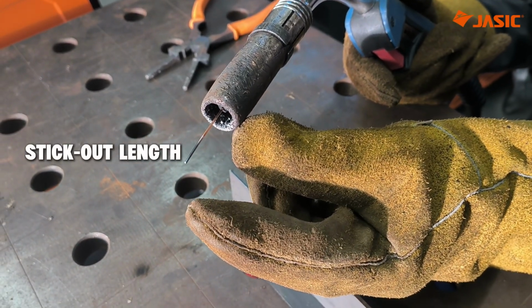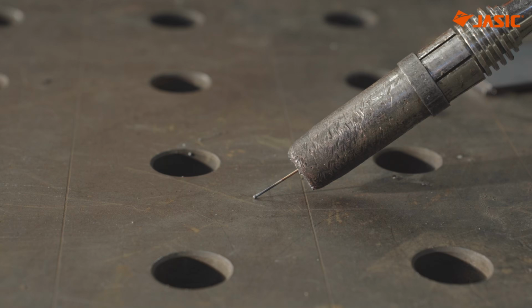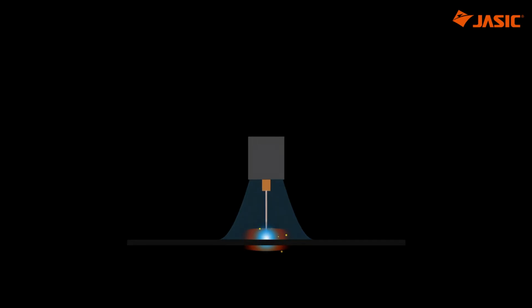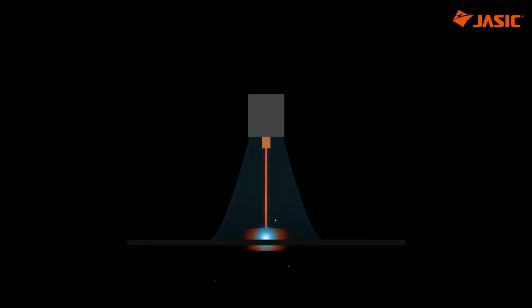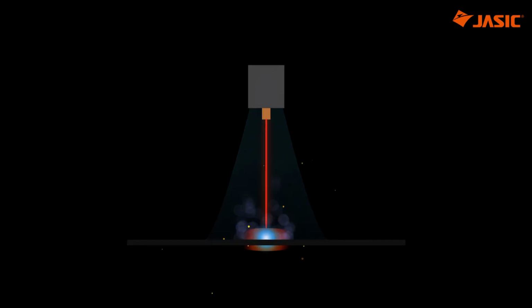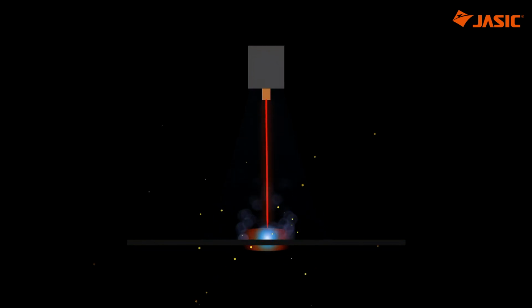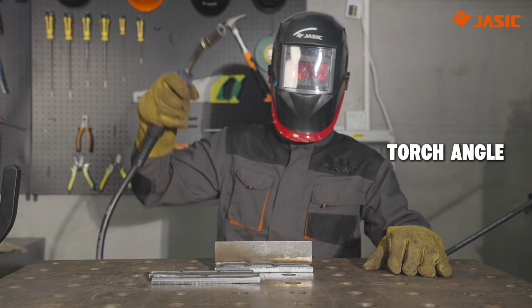The goal is to adjust the inductance until the arc sounds smooth while producing the least amount of spatter without sacrificing penetration. Stick out length also affects spatter. A typical recommendation is 10 to 15 millimeter depending on wire size and the welding process. If the stick out length is too long, the exposed wire is preheated by electrical resistance before reaching the arc. This overheats the wire, makes wire feeding less stable, and disrupts metal transfer, resulting in more spatter and sometimes arc instability.